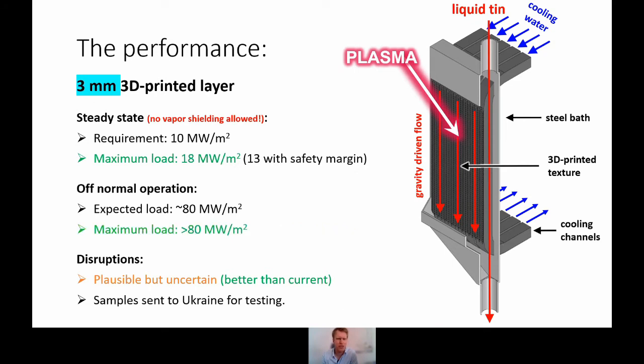So what happens if we go to 3 millimeter? The surface is thicker, it will heat up more easily. That's why in steady state, we have to reduce the maximum load to about 18 megawatt per square meter. In off normal operation now, the nice thing is, because the surface is a bit hotter and further removed from the cooling water, now vapor shielding allows us to deal with this 80 megawatt per square meter. So this is fantastic.